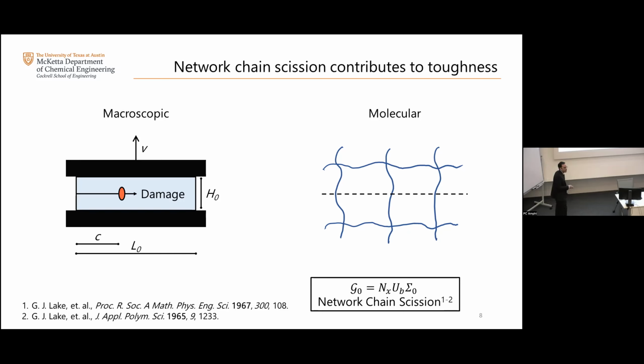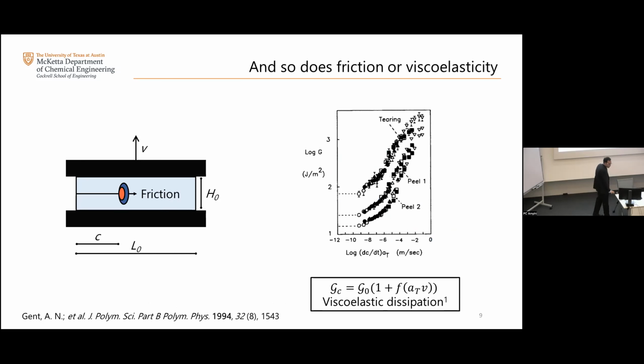And again, I'm going to come back to this. It applies to a single layer. So you have to only break one layer of polymer chains at a fully stretched configuration in order to propagate that crack. This picture is highly ideal because in reality, things are more complex. In reality, you actually have a damage ahead of the crack tip, but you can also dissipate elastic energy by other mechanisms. And one that is very common is friction, because we know polymers have dynamics that are important too.